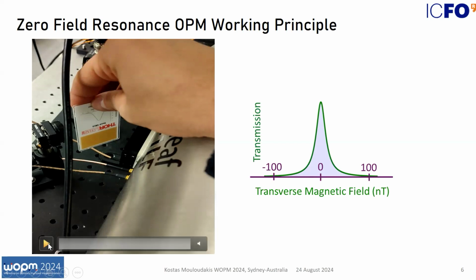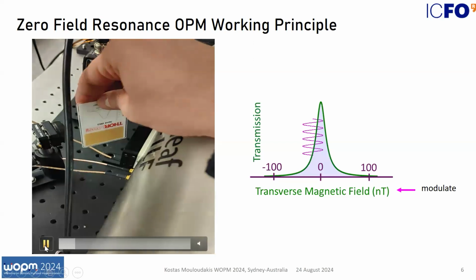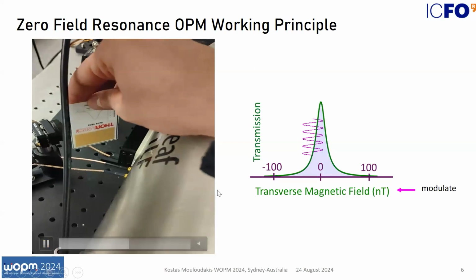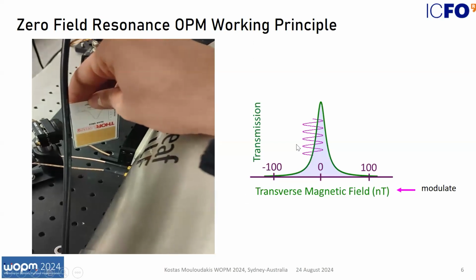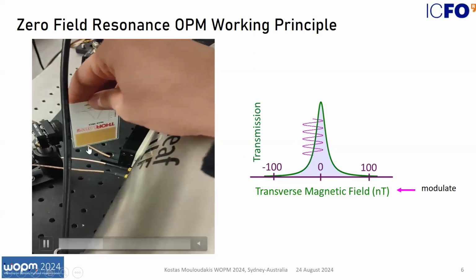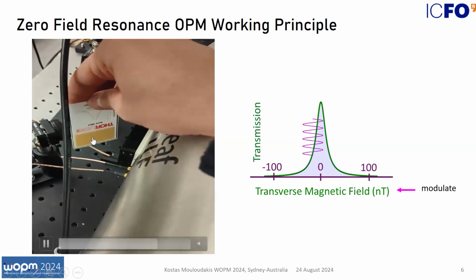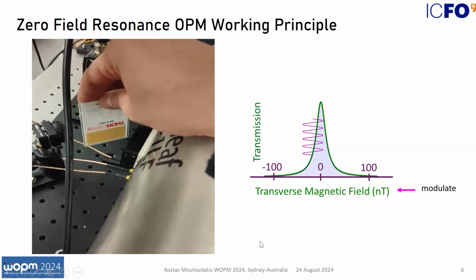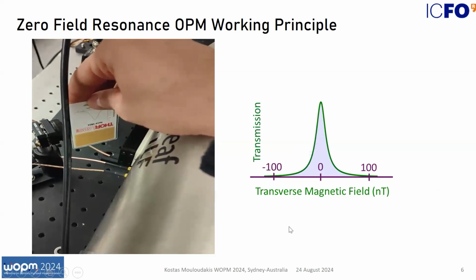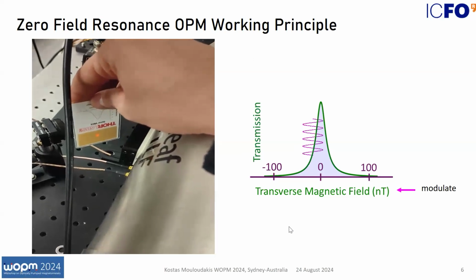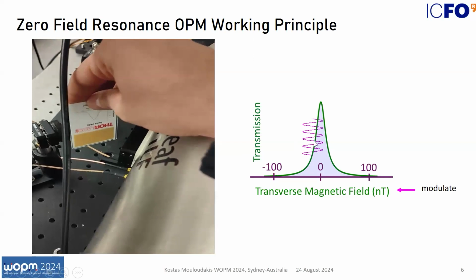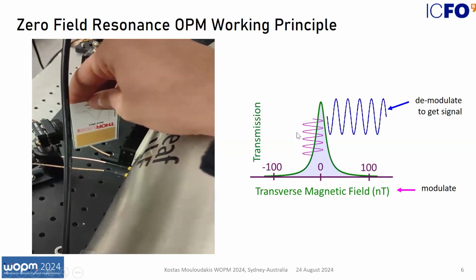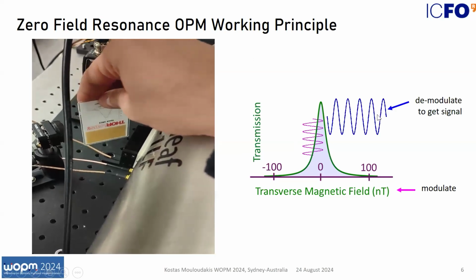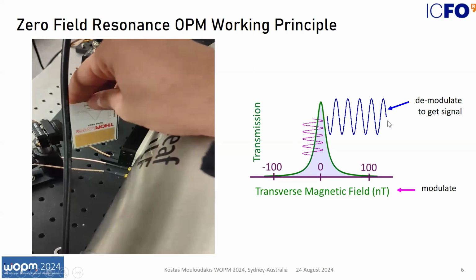Now, to operate this system, here I have a real-time implementation of this zero field resonance effect in the lab, where we can see that as we sweep the magnetic field around zero, we see this blinking, the transmitted light becomes maximum at zero field. Now, to operate this system as a magnetometer, we modulate the transverse magnetic field, and we demodulate the transmitted light to get the magnetometer signal.